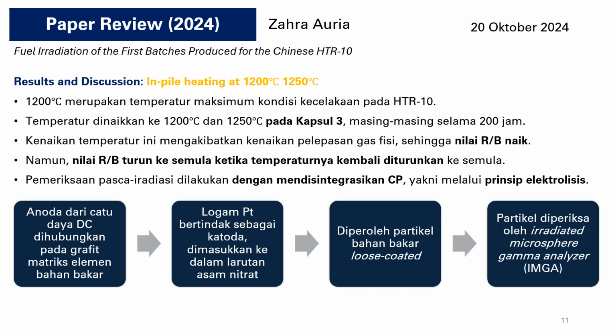The post-irradiation examination was done by disintegrating the coated particles through the electrolysis principle. Here we have a DC power supply that is connected to the graphite matrix of the fuel element. And here we have the platinum metal that acts as a cathode that would be inserted into the nitric acid solution. From that, we obtain the loose coated fuel particles, and those particles would be examined by the irradiated microsphere gamma analyzer, or IMGA.